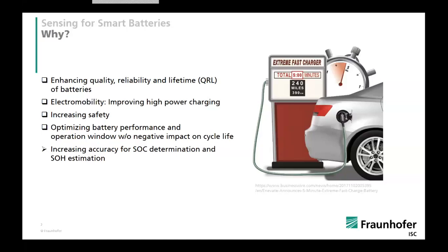And an additional factor is that we want to have this sensor that we develop here to be non-invasive and to be really attached on top of the cell, and no sensors like an optical fiber or a reference electrode within the cell. And the technique of choice we use here is the ultrasound time of flight measurement.